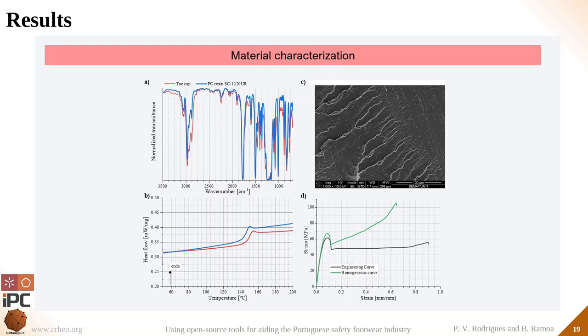Now, focusing on these three, we used polycarbonate resin that we had available in our laboratory, and comparing the spectroscopy peaks, you can see almost a perfect match between the principal peaks of polycarbonate, which allows us to deduce that the material used for the manufacturing of the toe cap was in fact polycarbonate. Given this initial assessment, we then need some other tests to corroborate this.